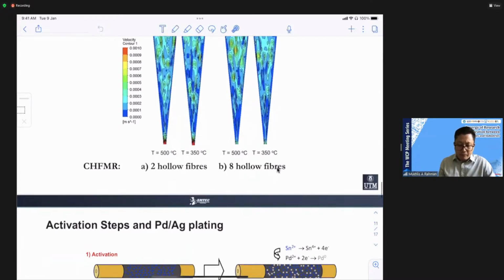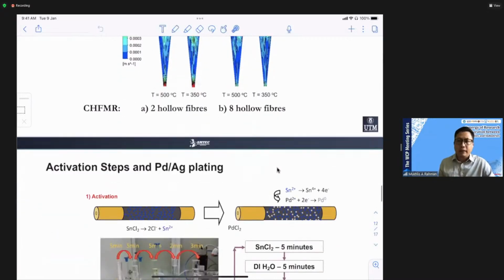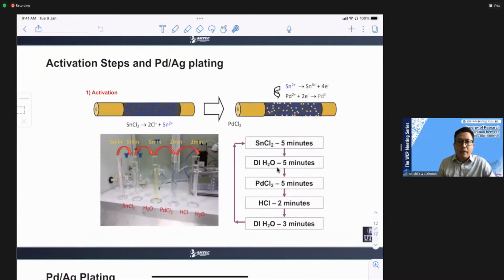So the next step, after we deposited our catalyst, is to coat our membrane with palladium. To perform the coating, we use the electroless plating technique. For this purpose, we tried sputtering of palladium, but during the reaction process, the palladium prepared using sputtering burst, because there is no interaction between the palladium membrane and the support. So we need to do activation first. We need to put a seed of palladium on top of our ceramic membrane.